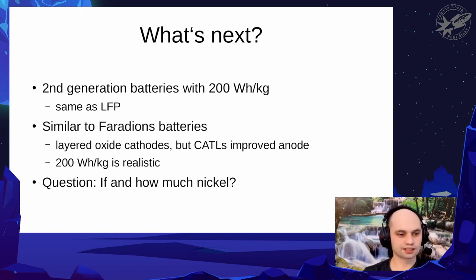Next is the second generation that was announced. It will be about 200 watt hours per kilogram, similar to LFP. This is a similar performance to what Faradion is already demonstrating using layered oxides, but if you just exchange the Faradion's own anode materials with what CATL has announced, you already get to 200 watt hours per kilogram. So this is kind of quite realistic.